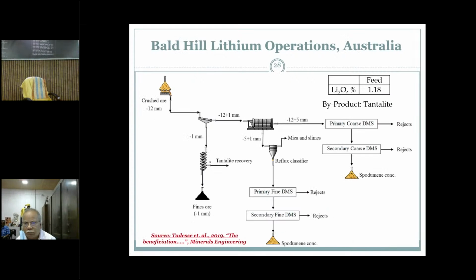Here is the last flow sheet I am going to show you, on Bald Hill lithium operations of Australia. The feed is containing about 1.1% Li2O, which has been subjected to screening, followed by a double deck screen and trommel. The coarse fraction is subjected to dense medium cyclones, dense medium separation, and the lighter particles will be rejected. The heavier fractions will be subjected to again DMS separator. The spodumene concentrate in the coarse fraction is being achieved, and the fines fraction is subjected to reflex classifier, followed by fines two stages of DMS separators to achieve the spodumene concentrate again.